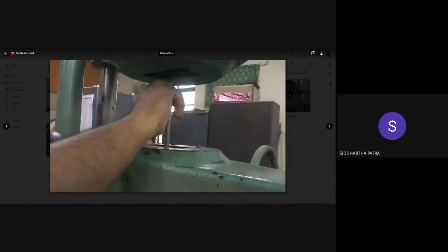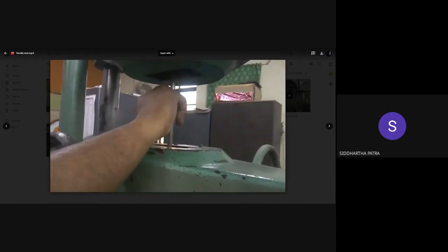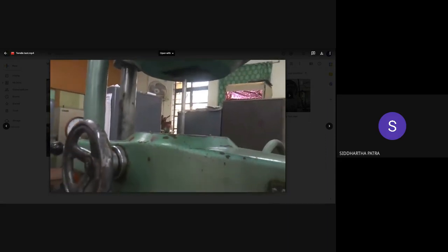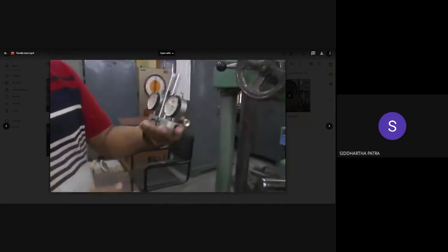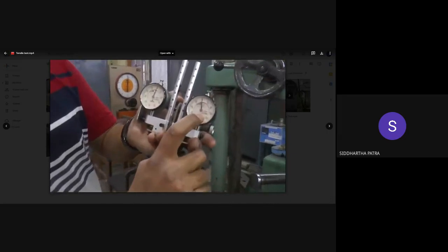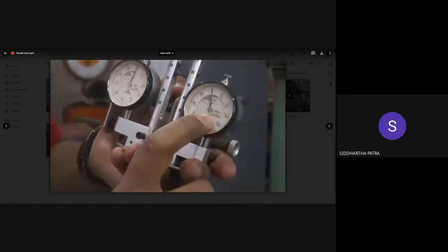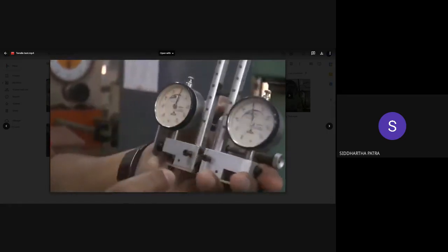So we will be taking only 1/3 of that length in the middle of the rod, which would be around 60 millimeters, and that's why we attach the extensometer. The least count for the extensometer, you might notice, is 0.01 millimeter. Okay. Now how does the extensometer work?